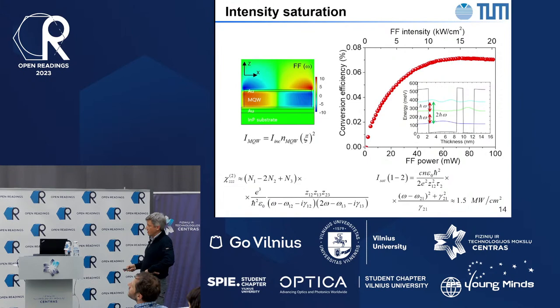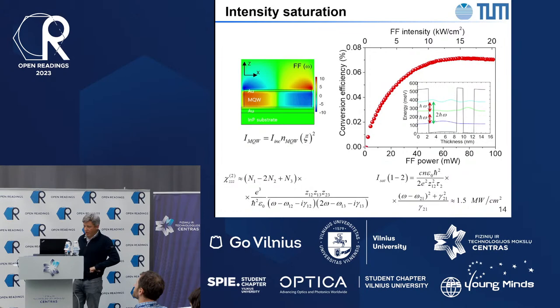One can also calculate the saturation intensity in these quantum wells, and you get something like 1.5 megawatt per square centimeter. That's the intensity inside of the multi-quantum wells. And since we have about 10 times field enhancement, that is, we have 10 times stronger field in this nanoresonator compared to the electric field in the impinging light, the 1.5 megawatt per square centimeter intensity in the quantum wells is achieved at only 15 kilowatt per square centimeter of the input. And that's roughly where we observe the saturation effect.